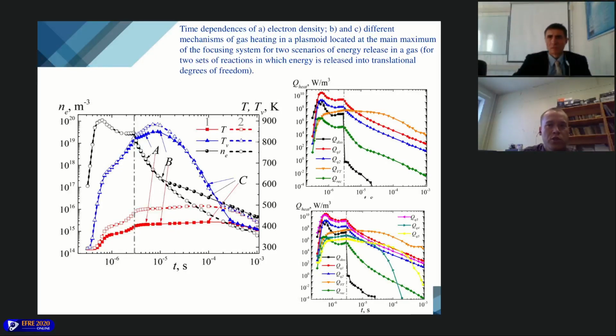A qualitatively similar form is observed in the behavior of the electron density as well as the vibrational and translational temperatures, but there are differences in the quantitative values. After reaching the maximum of the electron density, its weak decrease is observed, and the approach to a close to equilibrium value. Then after turning off the microwave electromagnetic field, the electron density begins to drop sharply in the interval from 3 microseconds to 10 microseconds. In the time interval from 10 microseconds to 1 millisecond, the electron density decreased by another 2 orders of magnitude for the first set of gas heating mechanisms, and by 3 orders of magnitude for the second set.